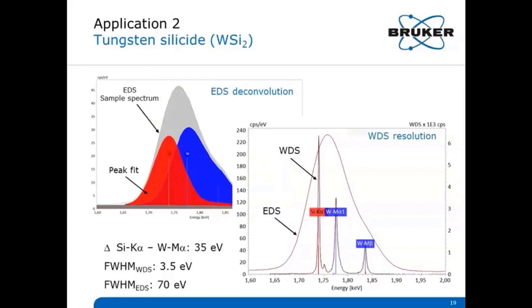Here we see WDS. The respective energy range scan is shown in the diagram on the right-hand side. WDS clearly resolves the silicon K and tungsten M lines. Resolution of silicon K is 20 times better by WDS than by EDS. Deconvolution is thus not necessary for WDS. The single peaks are nicely separated.